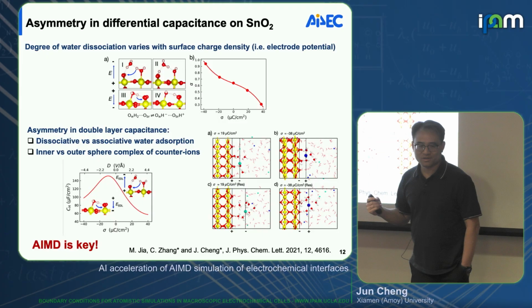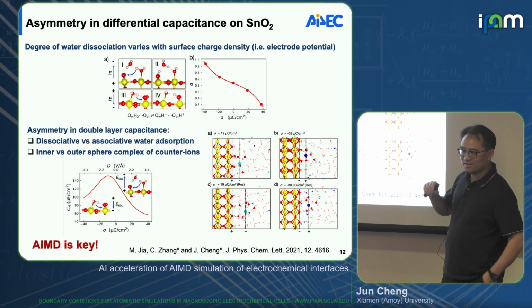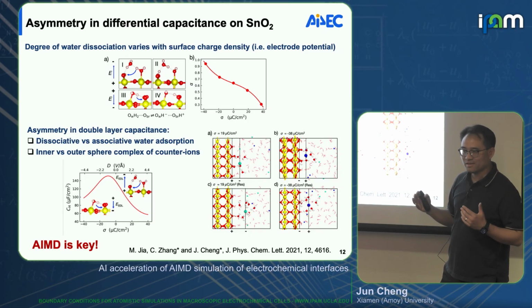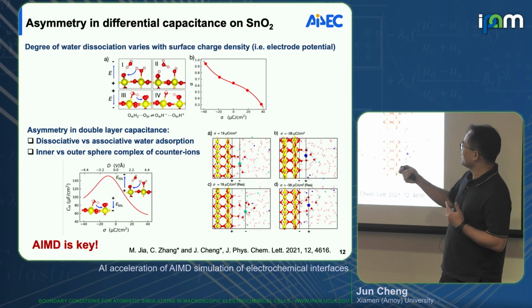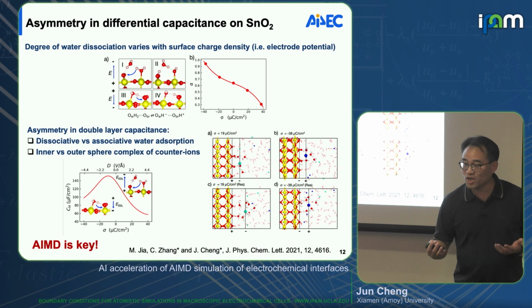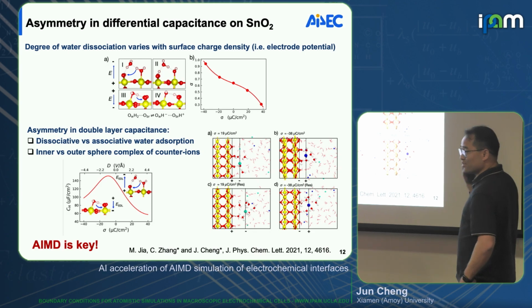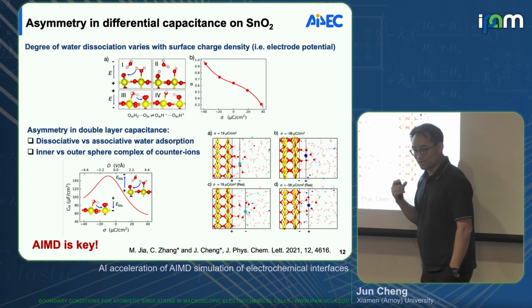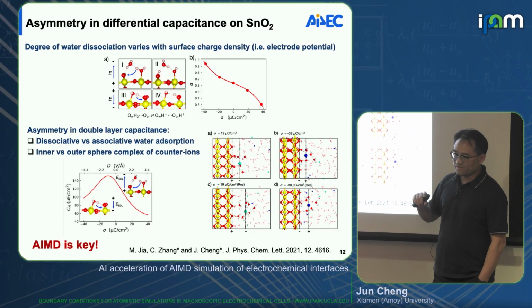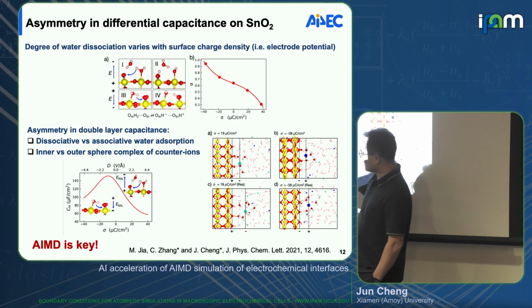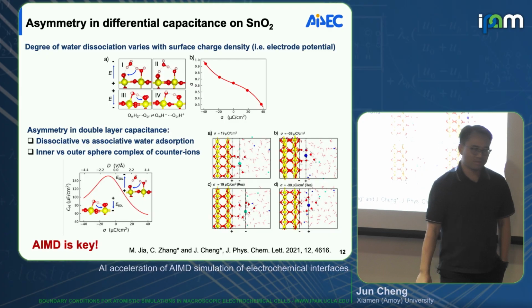the water structure, again, changes. In this case, it's due to the acid-base chemistry. The water dissociates. The degree of water dissociation changes. That, again, gives you a dielectric response due to the different interfacial potential induced by the molecular water and the dissociated water. That will, again, give you this bell-shaped